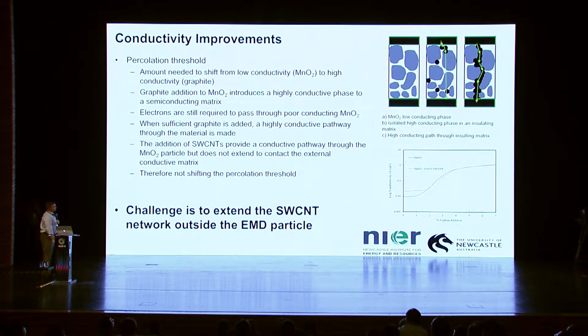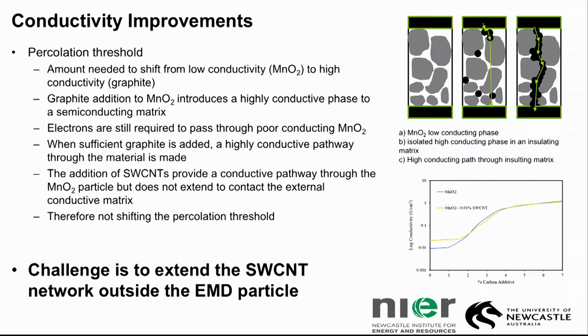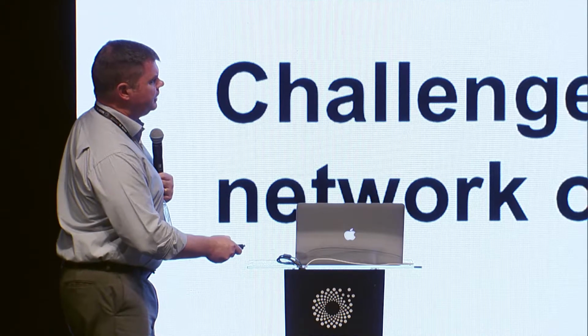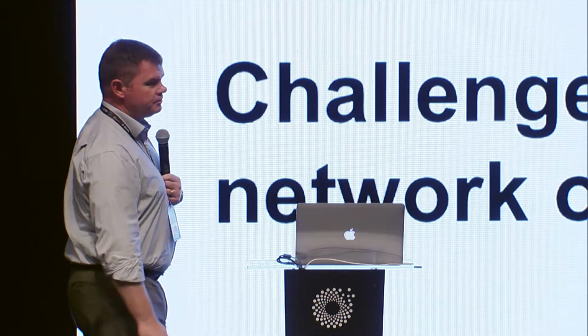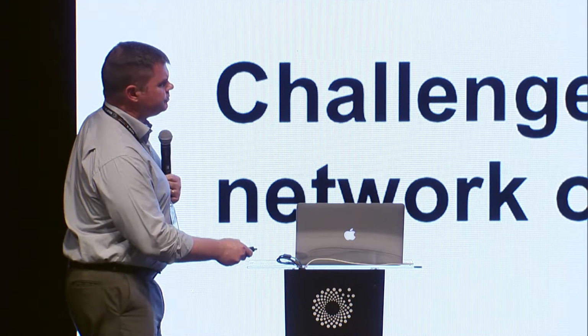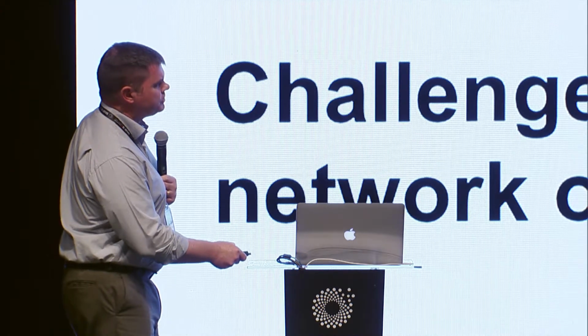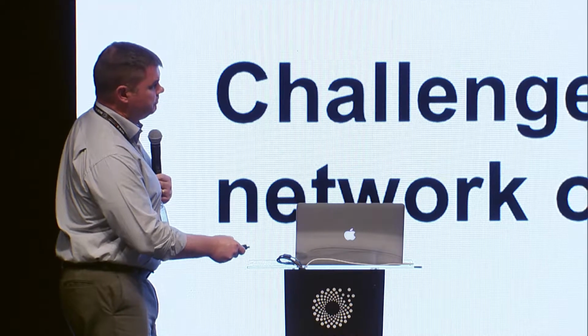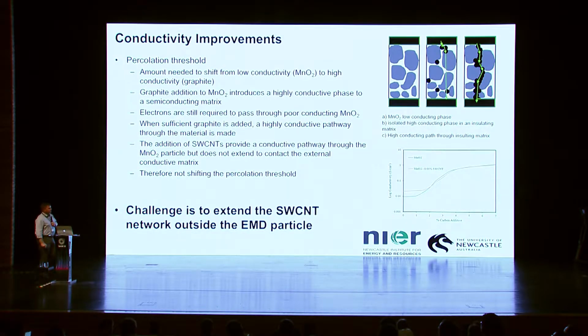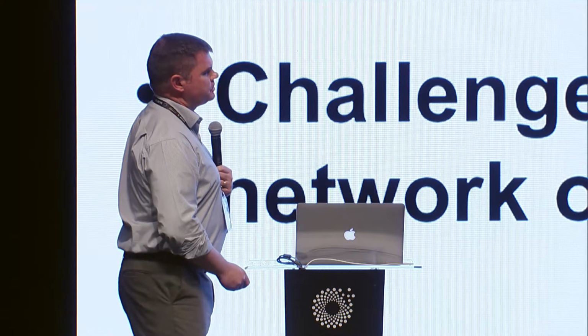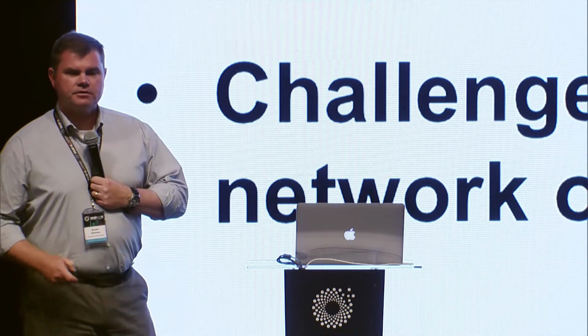Okay. What about a couple of other comments about the conductivity of these materials? We've looked at these in terms of their percolation threshold to try and determine the optimum amount of material that's being included. You see over here, we have percent carbon additive included versus the log of conductivity. What we see here is that for the starting material, we do improve the conductivity, which is great. But still, nonetheless, we can't move the percolation threshold at this stage from its point for this particular system. So the conclusion there is that while we have intrinsically increased the conductivity of our manganese dioxide, what we haven't done is extended those carbon nanotubes that are included to the external conductive network.